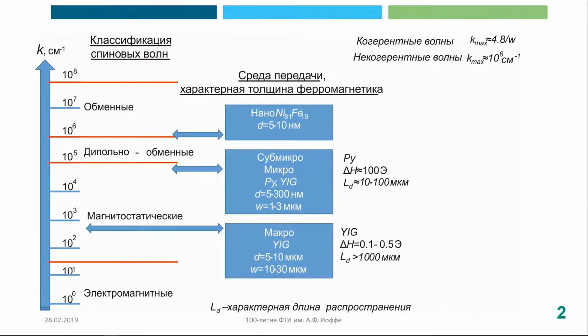And again, for nanometer scales, permalloy materials are probably the best candidates for this application. However, nowadays, yttrium iron garnet films we also can produce in the scale of nanometers. So there are methods for creation of films with a thickness of about 1 to 10 nanometers, and therefore lateral sizes about this size. And losses still, again, very small. Therefore, you can use these spin waves for various applications.